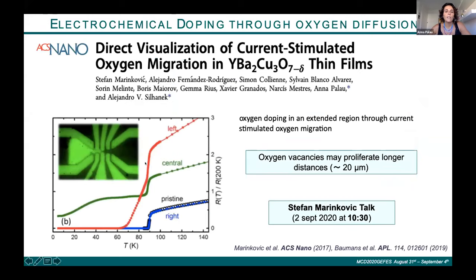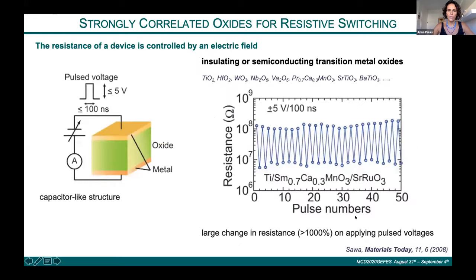And different experiments trying to see this motion of the oxygen induced by an electric field have shown, for example, in this very recent work of the group of Alejandro Silhanek, who were collaborating with us, that very large regions of the system could be modified, the oxygen in very large regions of the system could be modified by a field-induced oxygen motion, and in this case, by using current, producing what's called the electromigration effect. All this study will be explained in a couple of talks by Stefan at 10:30 in this same session.